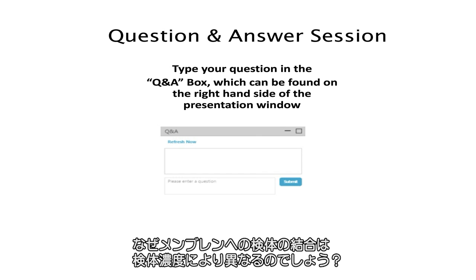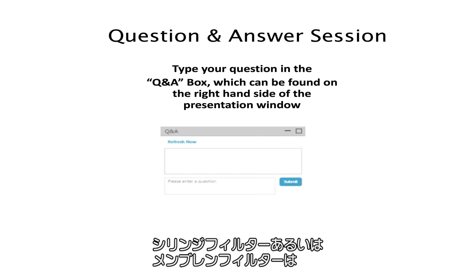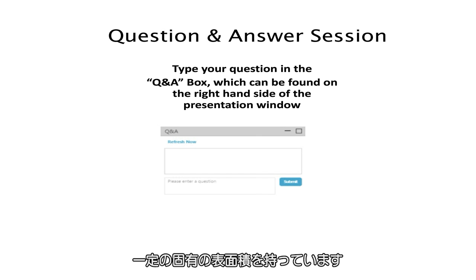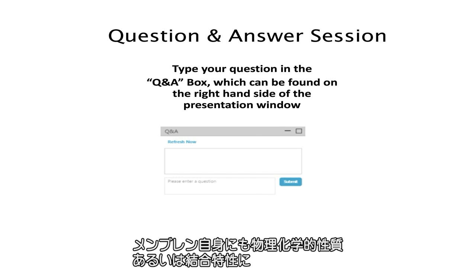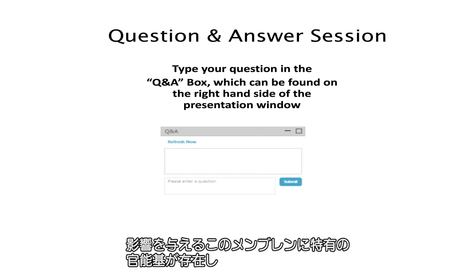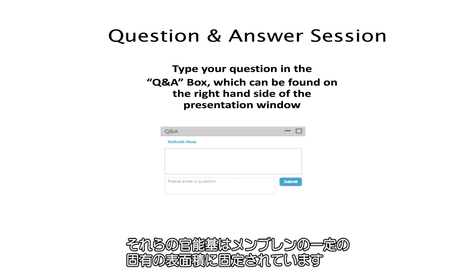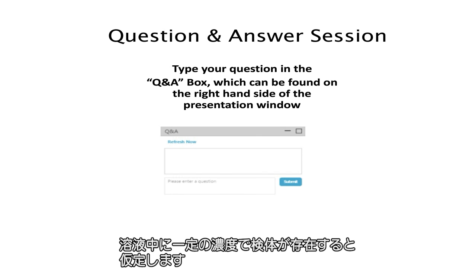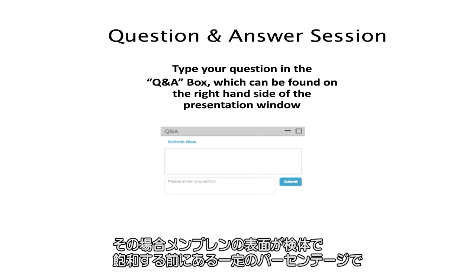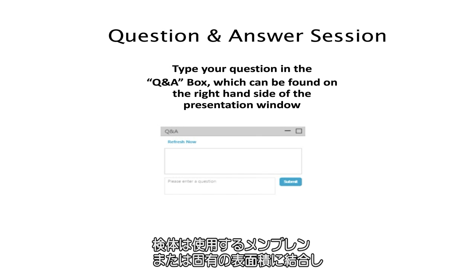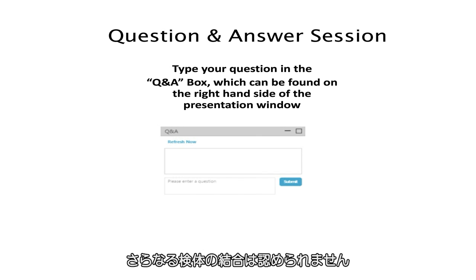Well, thank you. And why does analyte binding to membranes vary with analyte concentration? So a syringe filter or a membrane filter has a certain specific surface area, and the membrane itself has physico-chemical characteristics or functional groups that affect the binding characteristics of this particular membrane. And those functional groups are fixed in a certain specific surface area of a membrane. So when you have a certain concentration of analyte present in your solution, a certain percentage of this analyte will bind to your membrane before the membrane surface gets fully saturated with your analyte, and no further analyte binding is observed.